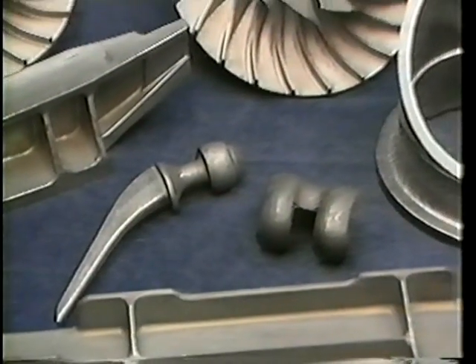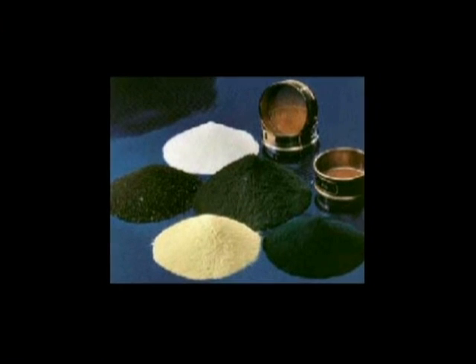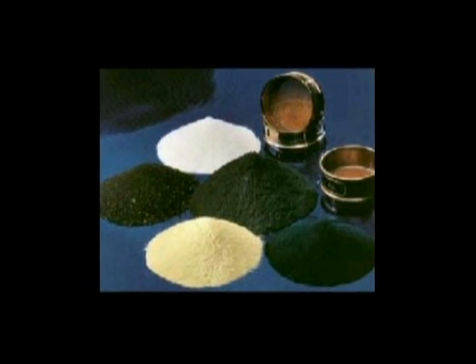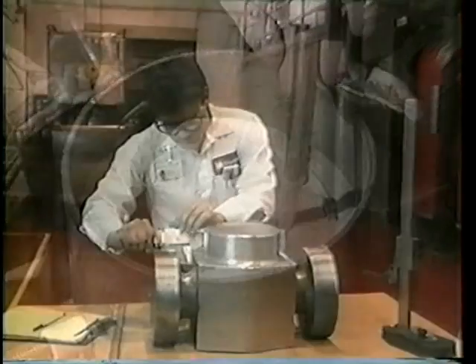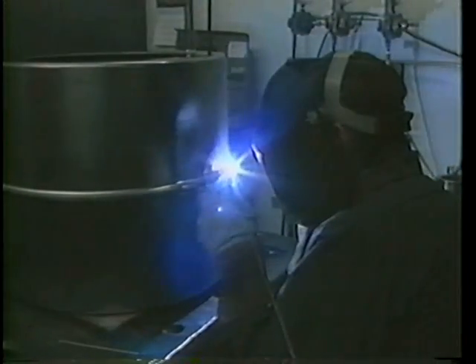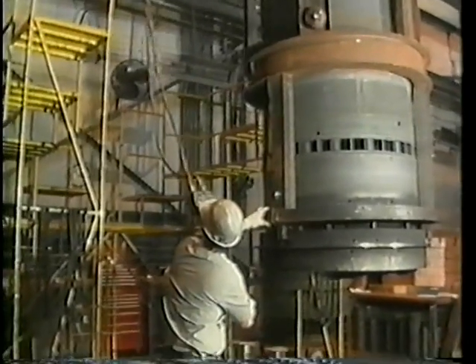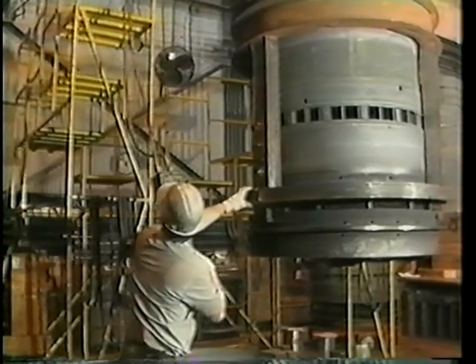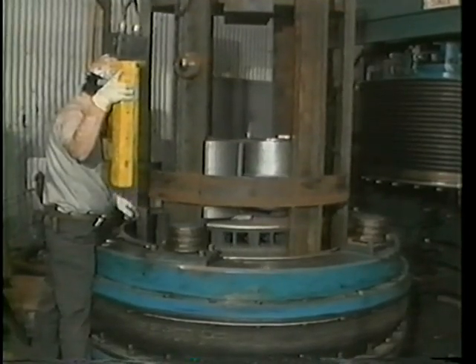The production of powdered metal components is one of the major applications of hot isostatic pressing. Powdered metallurgy creates specialized alloys with a fine-grained microstructure and uniform purity. The alloy powder is loaded into precisely designed metal molds, which are then welded closed and evacuated to create an internal vacuum. The HIP process shrinks both the mold and powder, fusing the particles into a precise net shape. The elevated temperature imparts strength and cohesion to the part. In most instances, this simultaneous application of pressure and heat can eliminate the need for secondary machining or sintering operations.